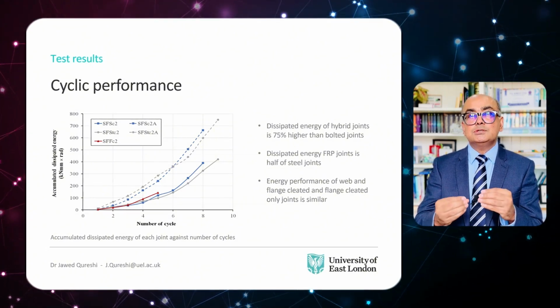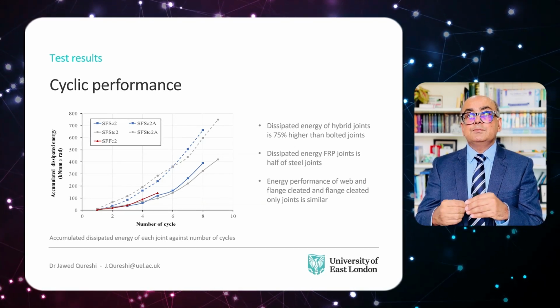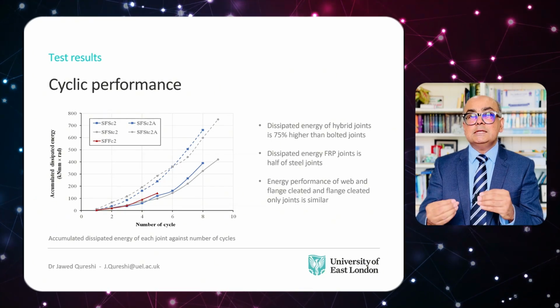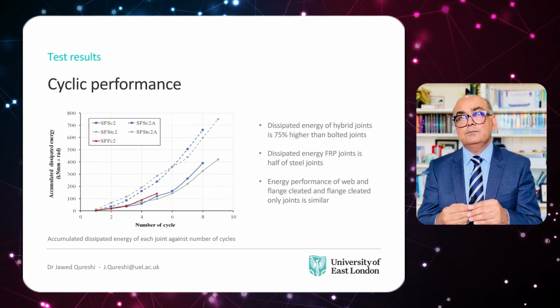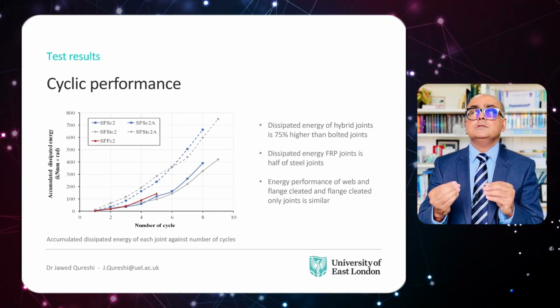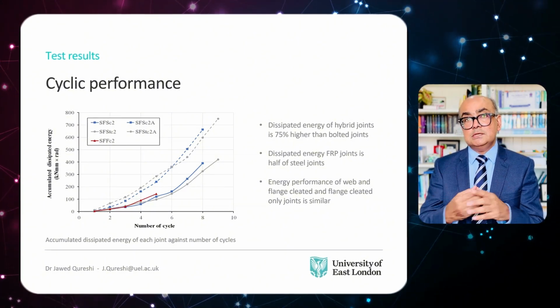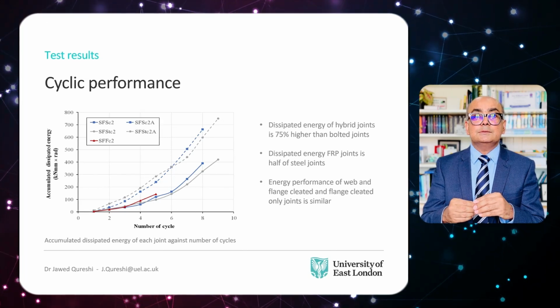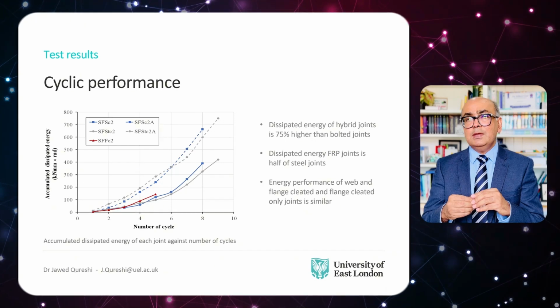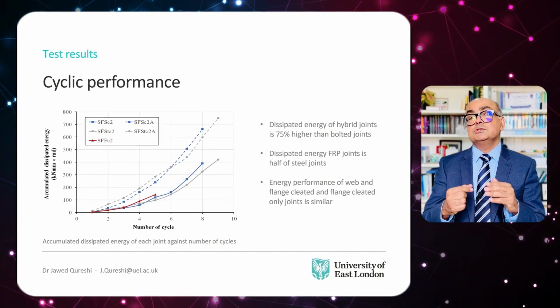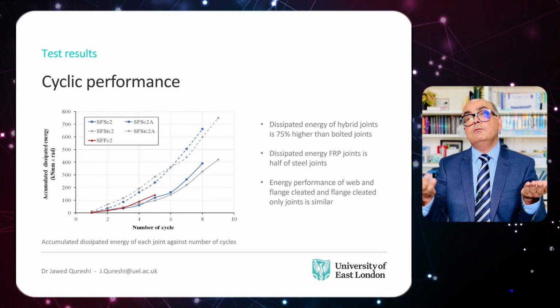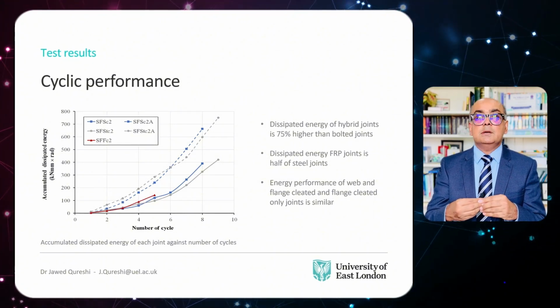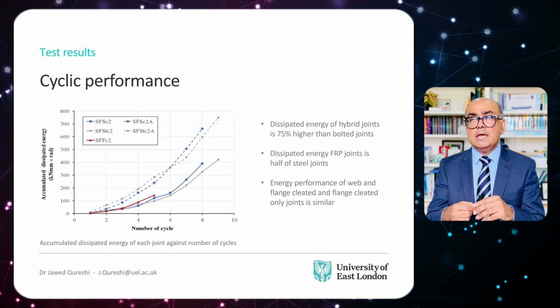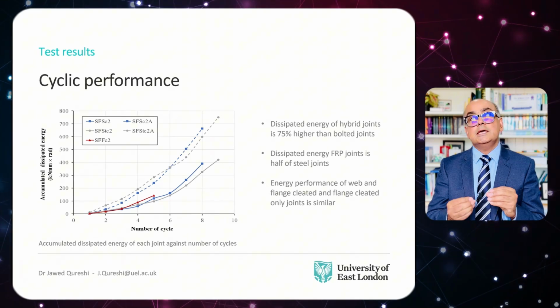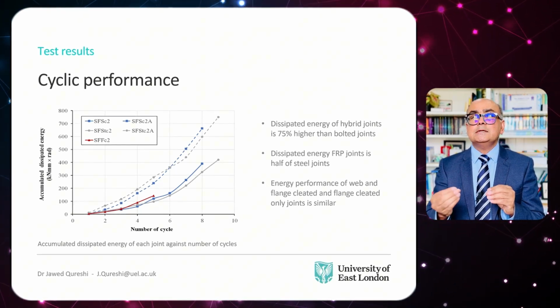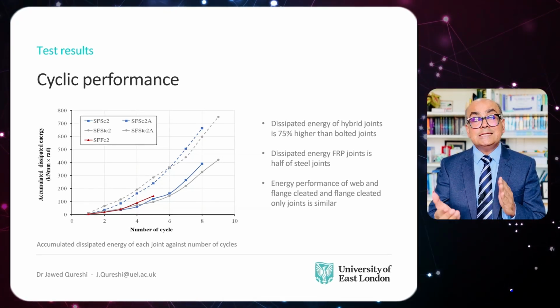Dashed lines here show hybrid joints and solid lines show bolted joints. Blue lines are joints with web and flange cleat and gray lines show only flange cleated joints. Joints with FRP cleat showed the worst overall performance in terms of dissipated energy, and this is pretty obvious from this graph. However, there are no differences in flange and web cleated joints compared to flange only joints, and the reason is that flange or web cleat on its own is sufficient to resist the applied loading. Hybrid joints showed as much as 75% more dissipated energy than bolted joints. Dissipated energy of FRP cleated joints is about half that of steel cleated joints.